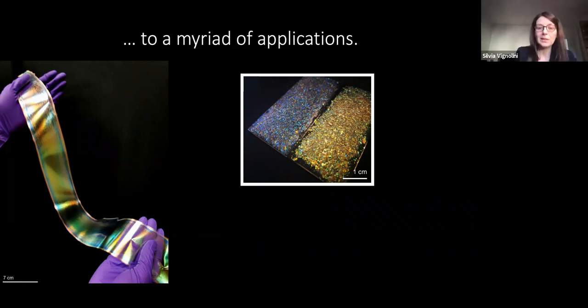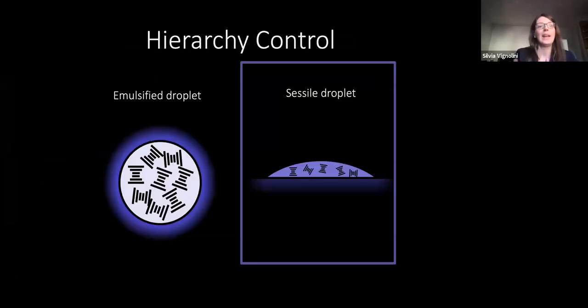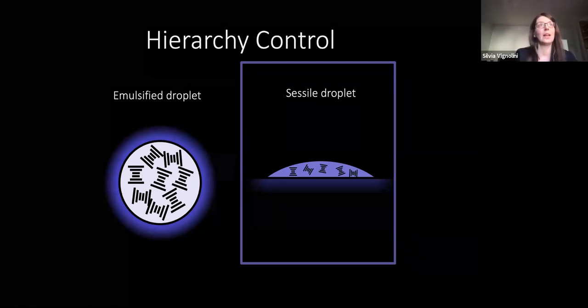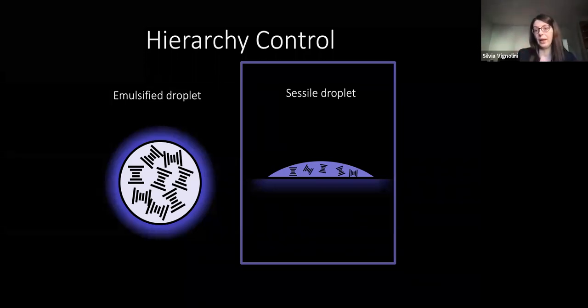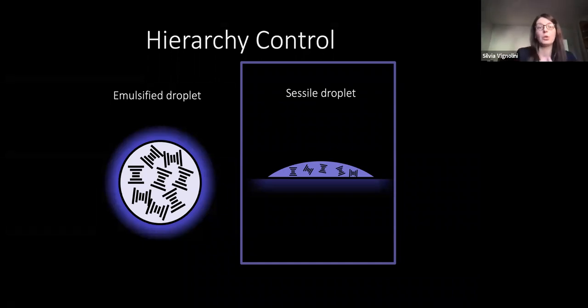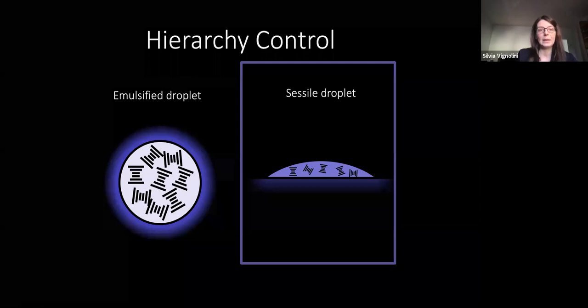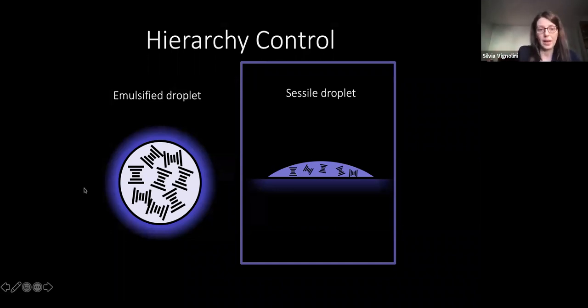But one thing I want to insist on a little bit, because I was showing you how the architecture matters in how you obtain the structure. I want to show you, using the cellulose nanocrystals, how the optical properties of this material and the visual response that you obtain can change as a function of what we call hierarchy. We call hierarchy the additional structure on the micron scale that we add to this material. So I'll show you two examples, one having droplets, so spherical types of structure, and the other having droplets that instead are evaporated on a glass slide.